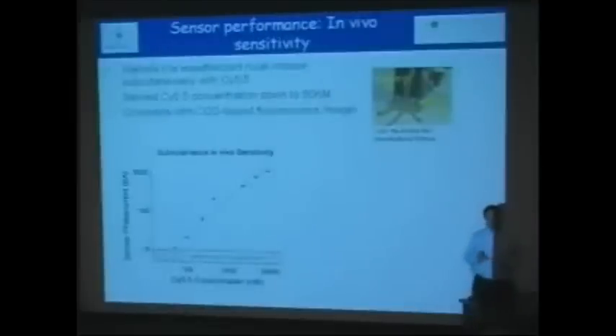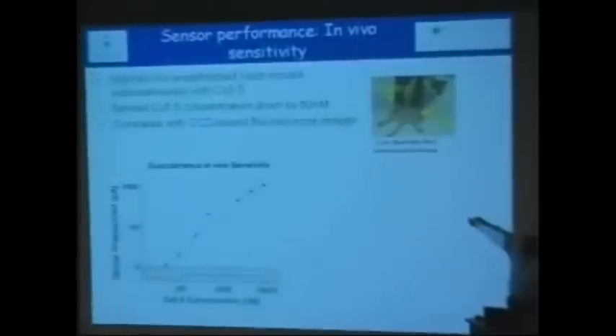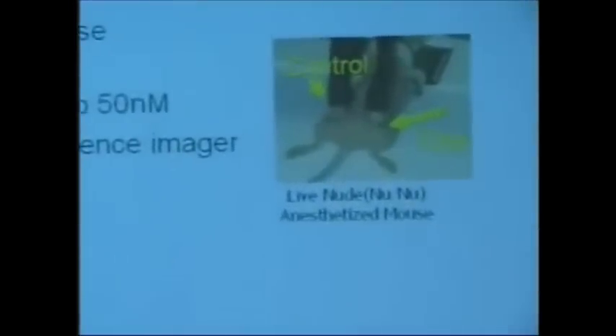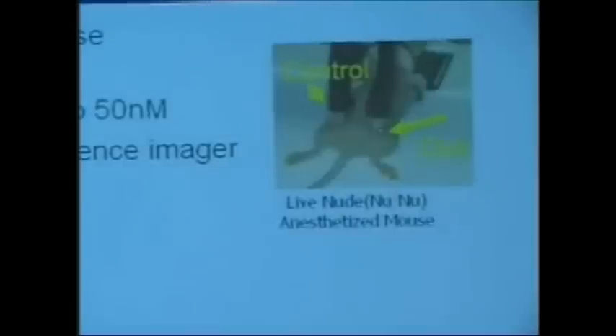Then we tried to do the same thing, but on a mouse. This experiment was done in collaboration with Sam Gambhir in his lab. You can see there are 2 lasers. Here it's shown in blue, but usually on my laptop it's shown much more as red, which is the laser light. So you shine the laser light in. This is the package for the sensor. In order to package it for robustness, we keep it in a standard TO can. Then you have one place where you want to measure and another place where you have a control, because if you have some movements, you would like to account for them. Then you can measure and plot the concentration on this axis while measuring the photocurrent.